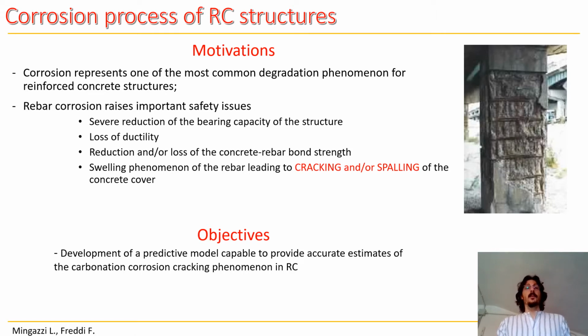Moreover, due to the formation of rust deposits around the reinforcement bars, a swelling phenomenon might happen, leading to cracking and spalling of the concrete cover. We decided to focus particularly on this last aspect, and we aim to develop a predictive model which is capable of providing accurate estimates of the carbonation-induced corrosion cover cracking problem for reinforced concrete structures.